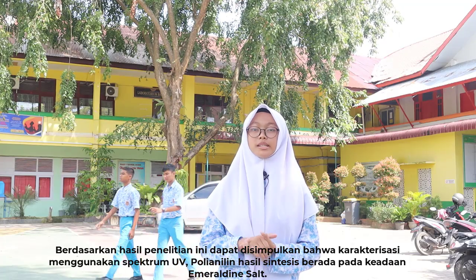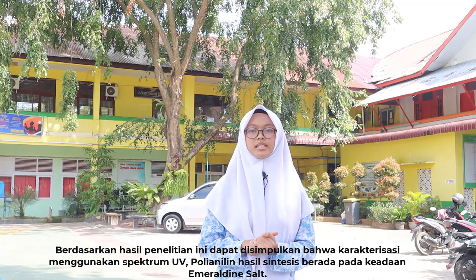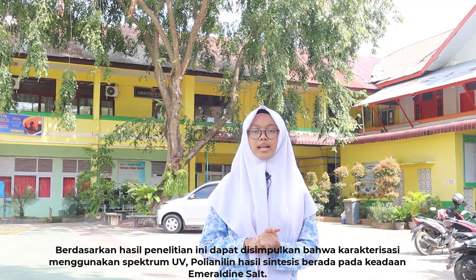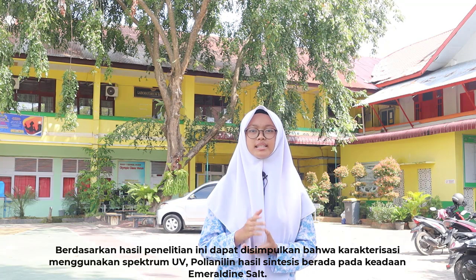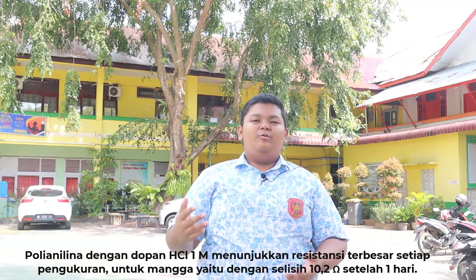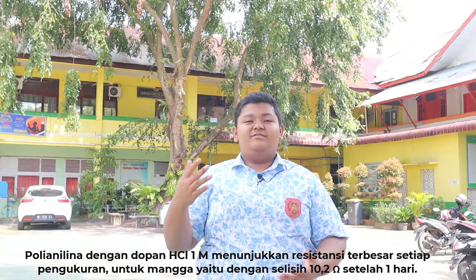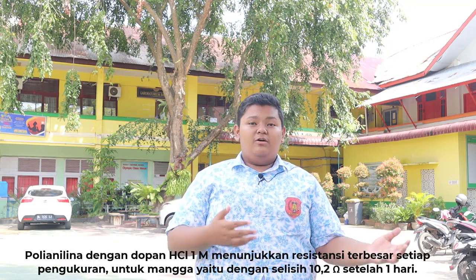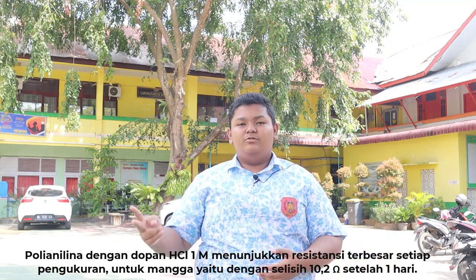Based on the result of this research, it can be concluded that characterization using UV spectrum shows that the polyaniline that results from the synthesis process is emeraldine salt. Polyaniline with 1 molar dopant showed the greatest resistance in the measurement. As for mango, there was a difference of 10.2 after 1 day.